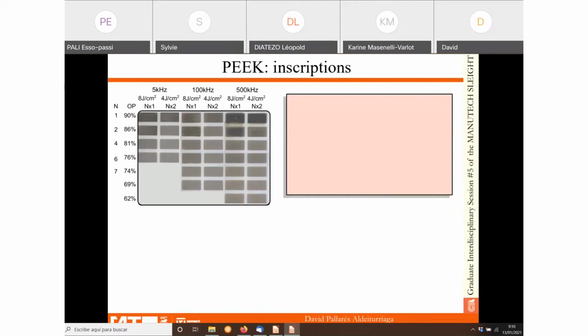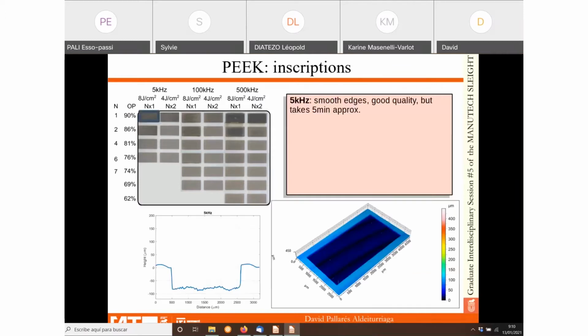That's the first thing. And for the second thing, well, if we take a look, for example, at this square, well, it looks nice, smooth edges, good quality. We can even say that this initial waviness is somehow being polished. It's lower, this waviness here. It hasn't disappeared, but it's still here, but it's lower. But it takes 5 minutes. Okay, we can't give to the industry something that takes so long. So we need to reduce this time.